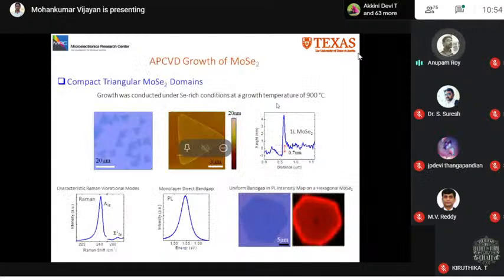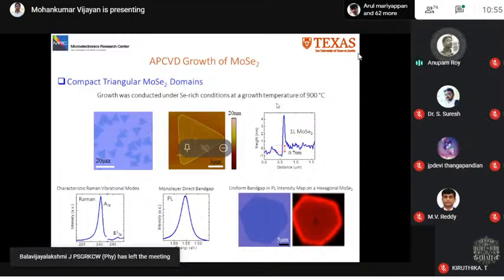So in the next slide, I show that in the optimized growth condition, that is at 900 degrees C, we get compact monolayer, triangular, or hexagonal MoSe2 domains. And you can see from the optical micrograph and atomic force microscopy images, and good Raman and PL characteristics, about 1.55 eV band gap and uniform band gap in the PL intensity map. So now the interesting thing in the next slide is that here I show the effect of growth temperature and the metal flux that can influence the growth morphology to deviate from the compact triangular or hexagonal modes.